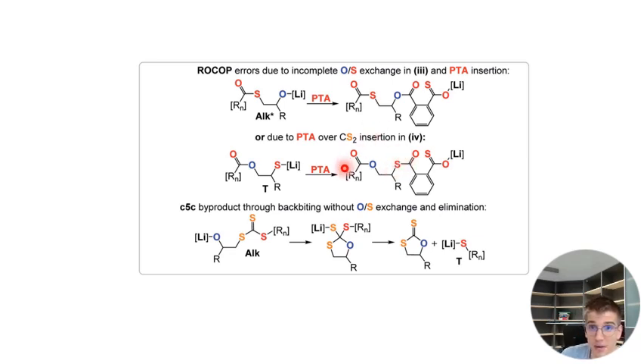Then there was this other byproduct, the cyclic dithiocarbonate, and this comes from, for example, when the lithium alkoxide, instead of propagating, bites back. So this attacks now here, forms another 5-membered intermediate, and that then eliminates here the thiolate to form the dithiocarbonate. Yeah, this is one pathway. The other pathway would be when an alkoxide next to a thioester would insert CS2, then propagate and then eliminate, by essentially the same pathway.